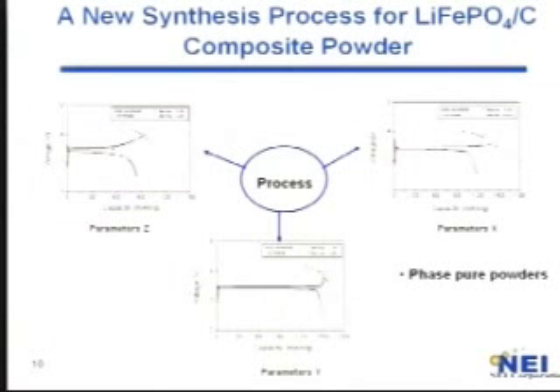step? And then we developed a new process, which is a single step process where the nano lithium iron phosphate and the carbon composite is produced in one single step. And the amount of carbon is maintained around 5-8%. And it depends. What this slide shows is that in the same process, by manipulating